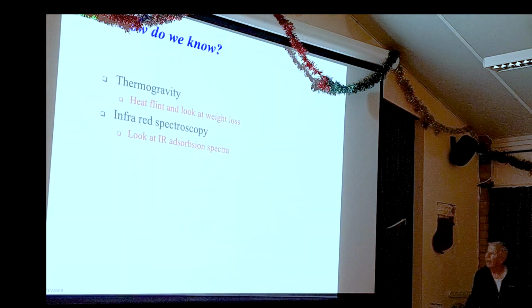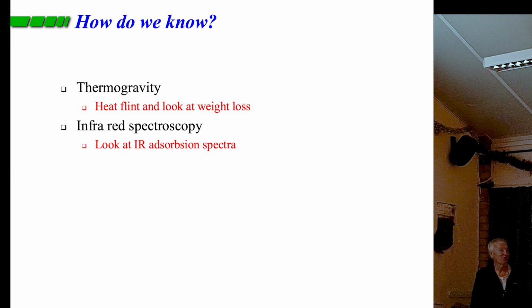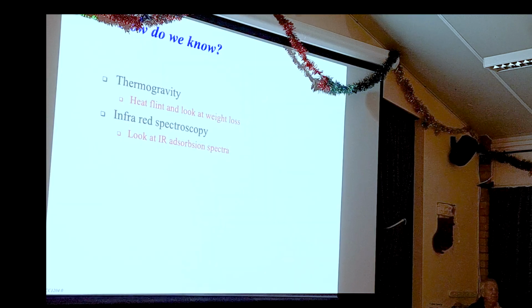Now, how do we actually know all this? I can see you thinking. Well, we've got two main tools we can use in the laboratory. The first one is a technique called thermogravimetry. What we do is take some powdered flint in a little capsule, just a few milligrams, and then we heat the sample up and we weigh it to see the weight loss as a function of temperature. We can also use infrared spectroscopy, and that basically works by shining infrared light, heat, at the sample and then monitoring what gets transmitted and what gets absorbed by the material.